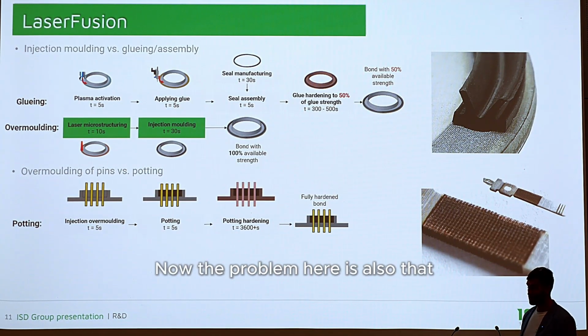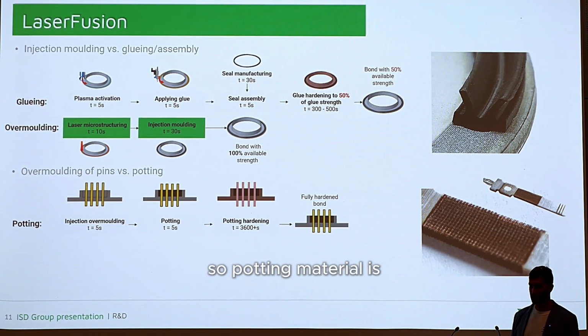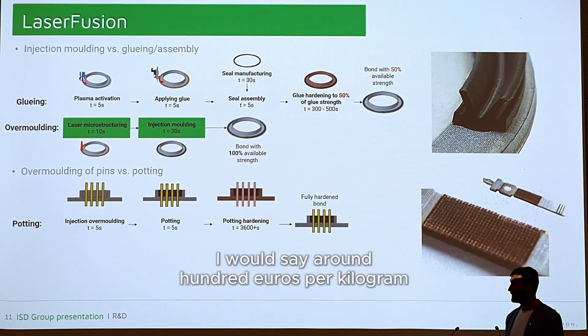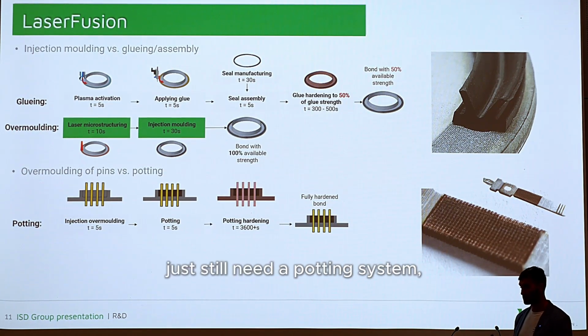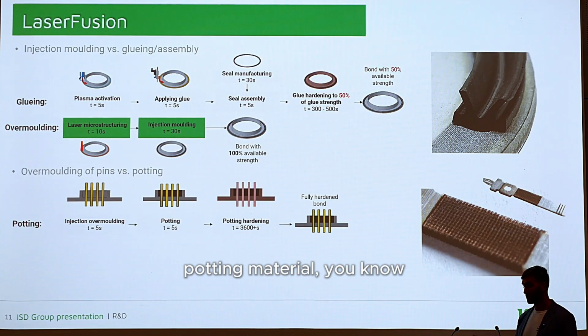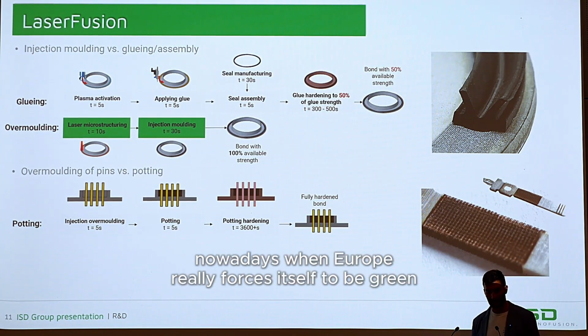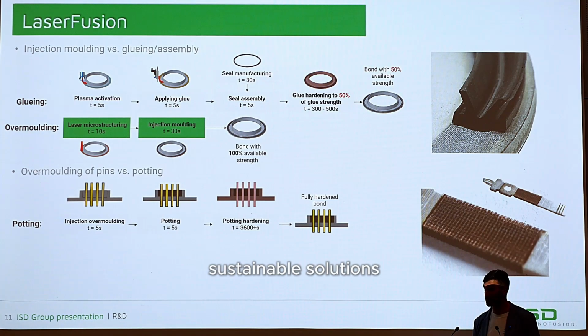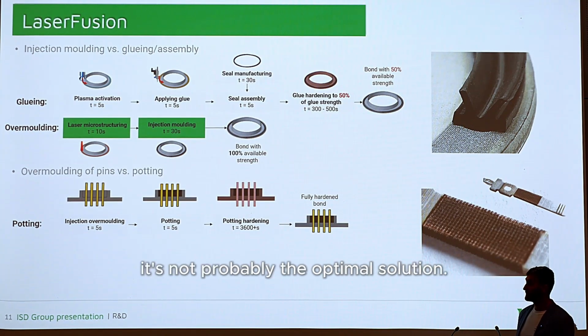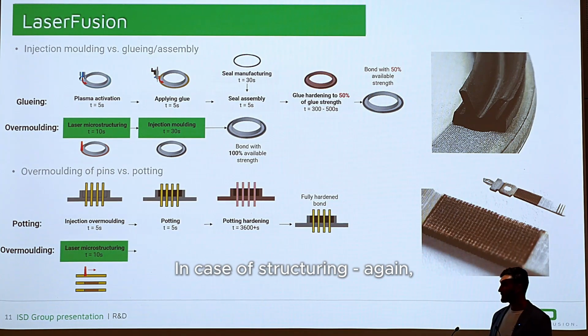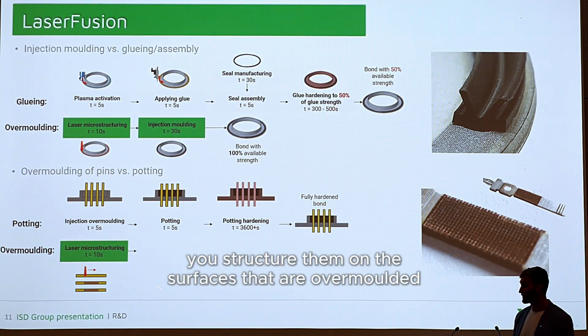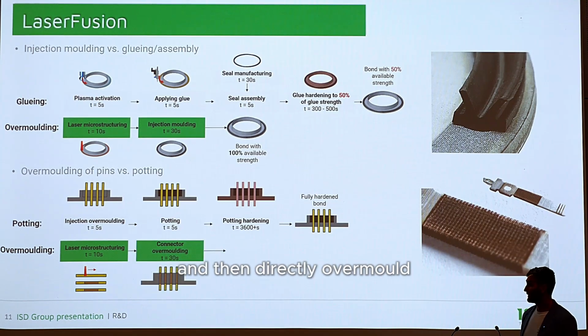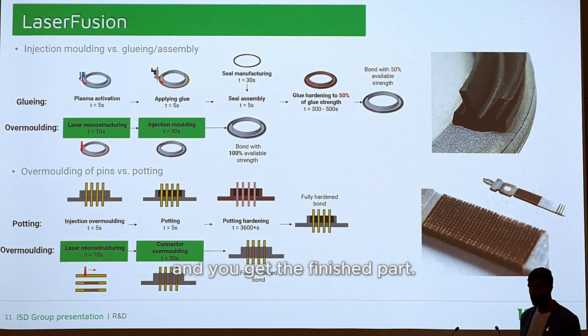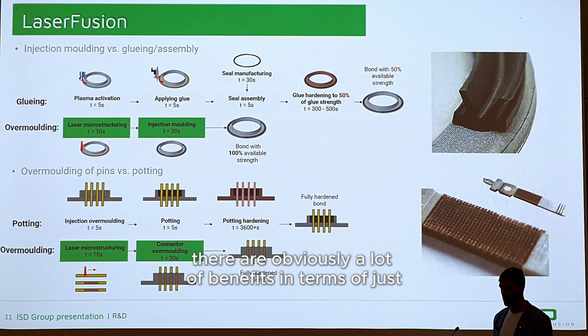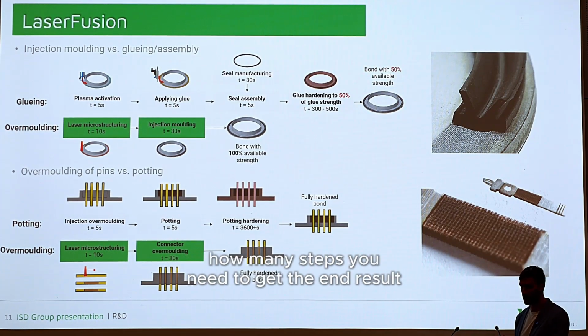Now the problem here is that potting itself is quite expensive. Potting material is around 100 euros per kilogram. Even though you need small dosages, you still need a potting system. And nowadays, when Europe really forces itself to be green and you need sustainable solutions, potting is probably not the optimal solution. In the case of structuring, again, you pre-prepare the pins, you structure them on the surfaces that are overmolded, and then directly overmold, and you get a finished part. So there are obviously a lot of benefits in terms of how many steps you need to get the end result of the finished product.